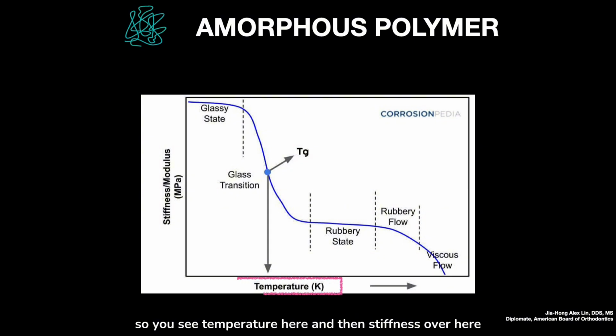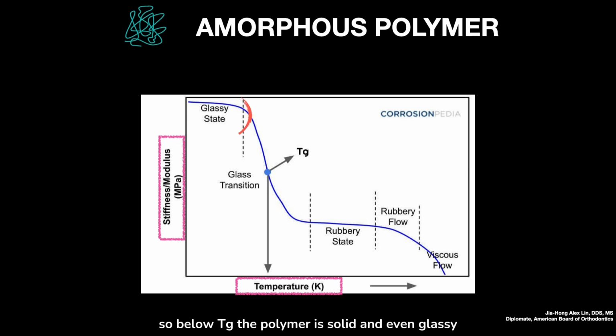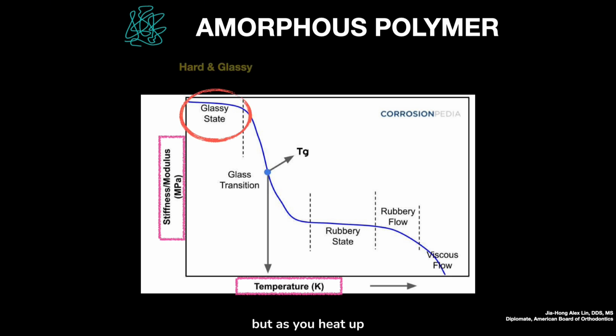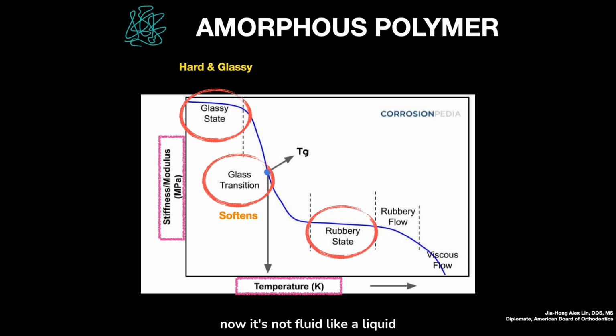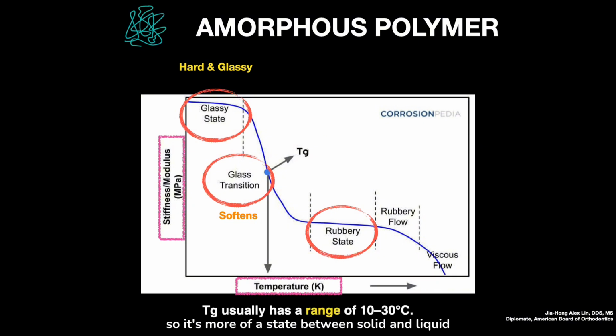So let's use this graph for explanation. You see temperature here and then stiffness over here. So below Tg, the polymer is solid and even glassy. But as you heat up and enter glass transition temperature, the amorphous polymer softens and the whole thing becomes rubbery. Now it's not fluid like a liquid, but it's not hard and glassy like the solid state that we usually see. So it's more of a state between solid and liquid. And remember, Tg is not a specific temperature. Rather, it has a range of 10 to 30 degrees. So it's a range instead of a melting point, which is very specific.